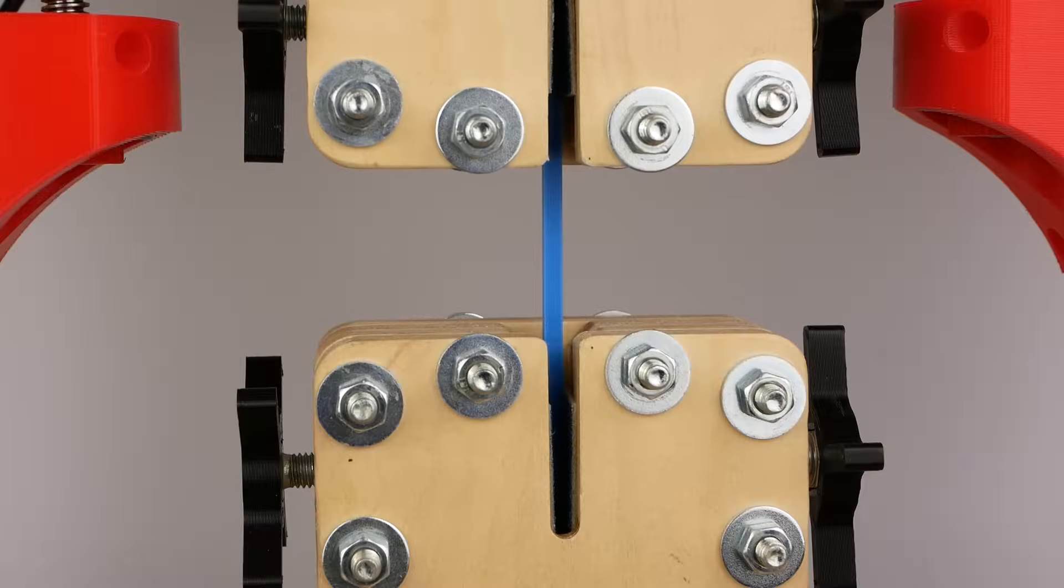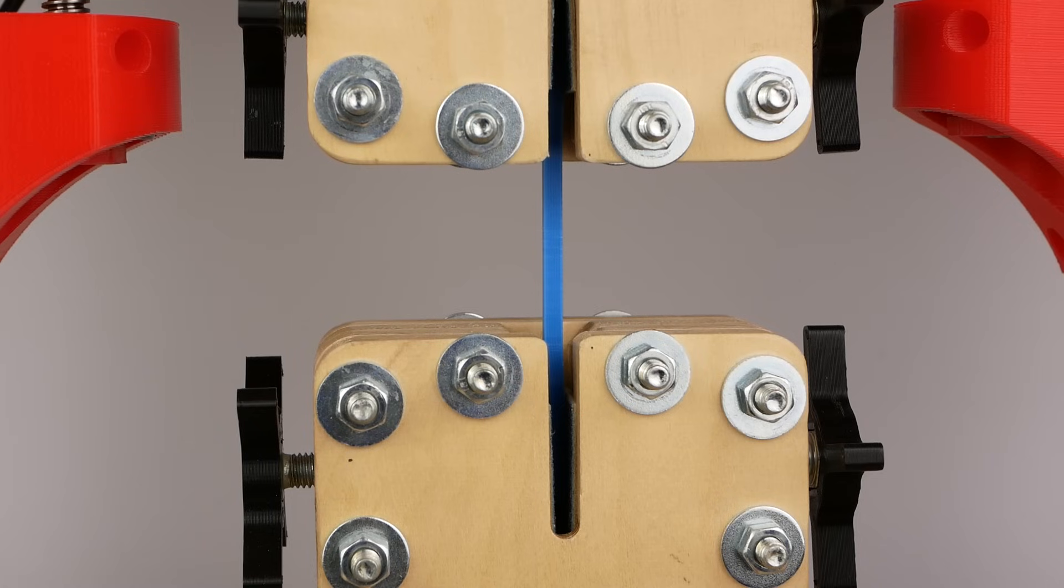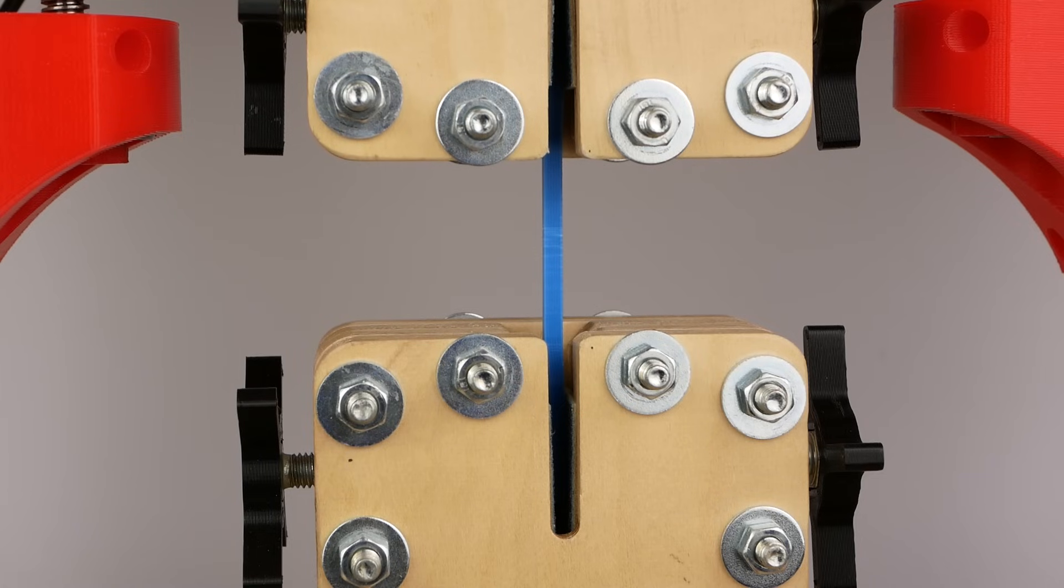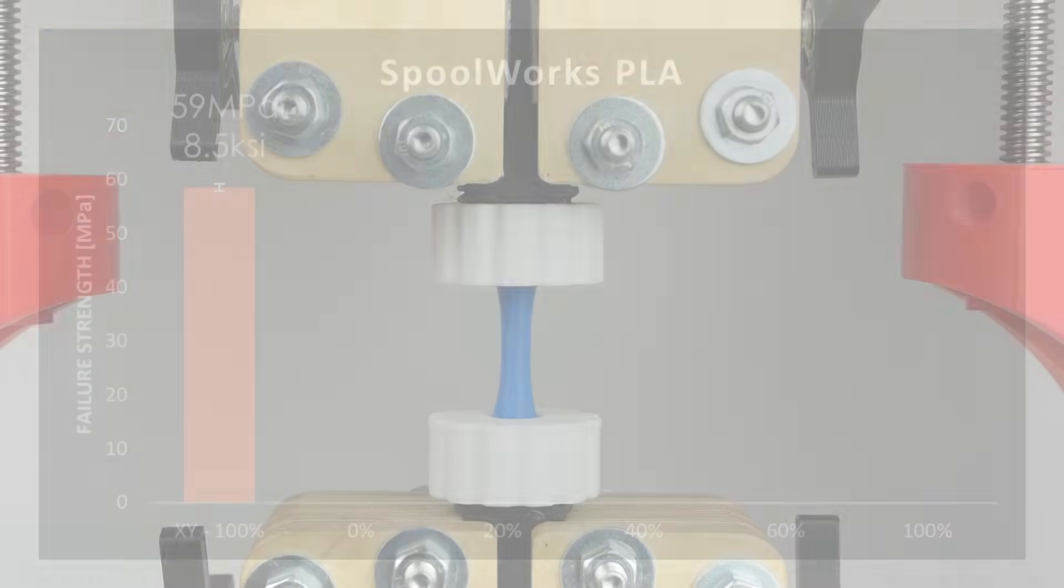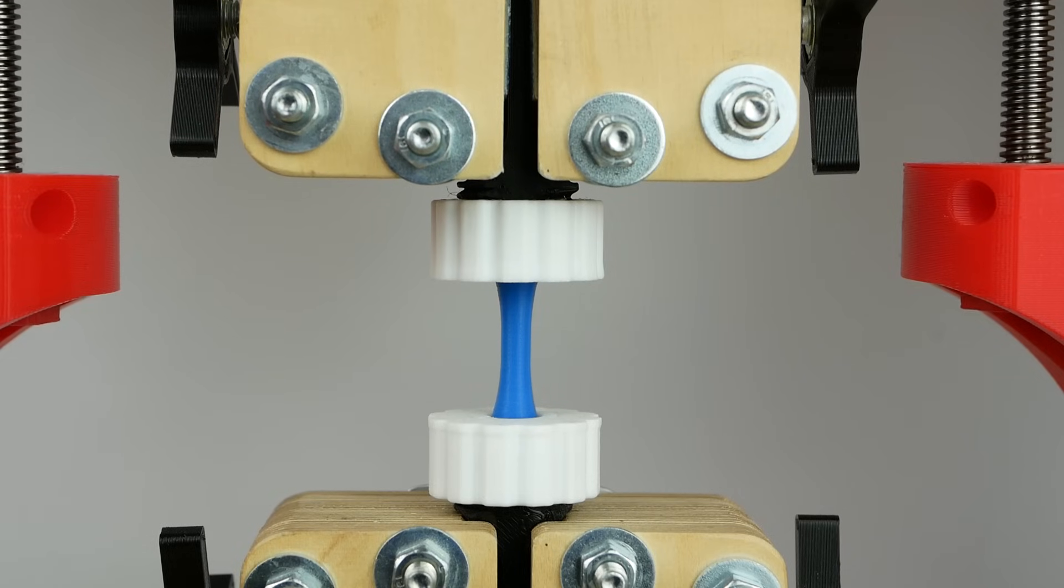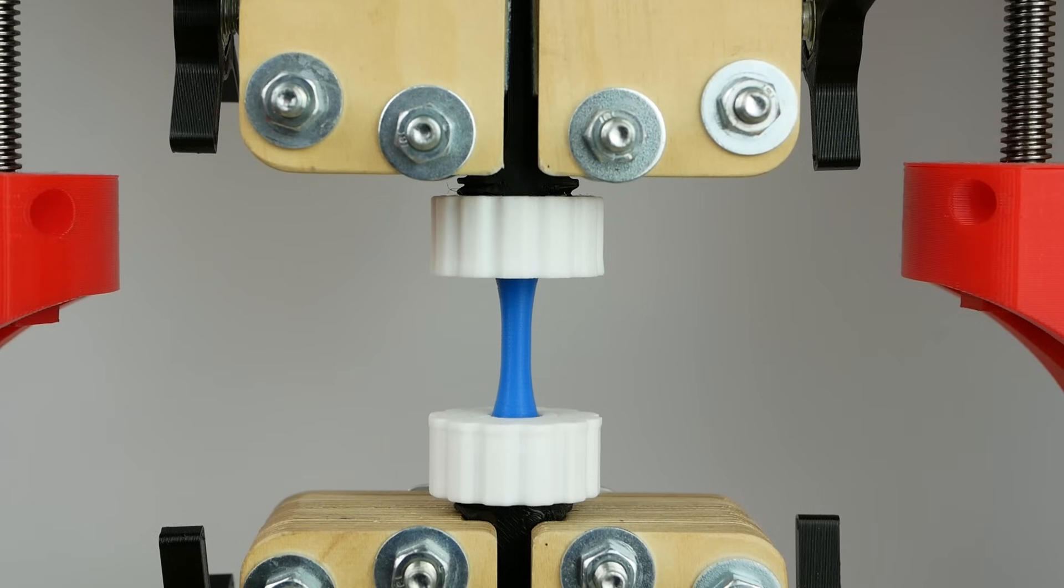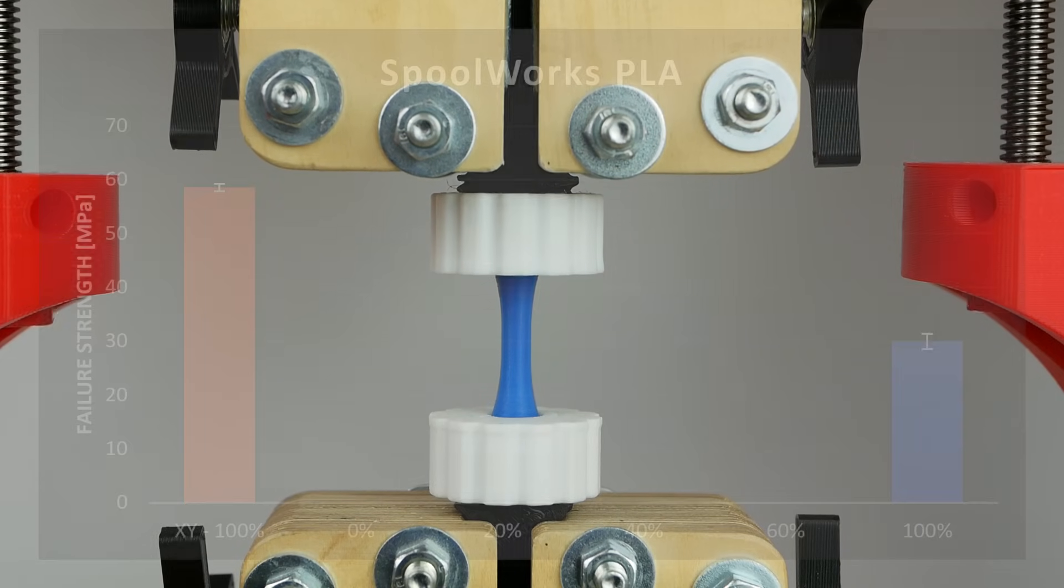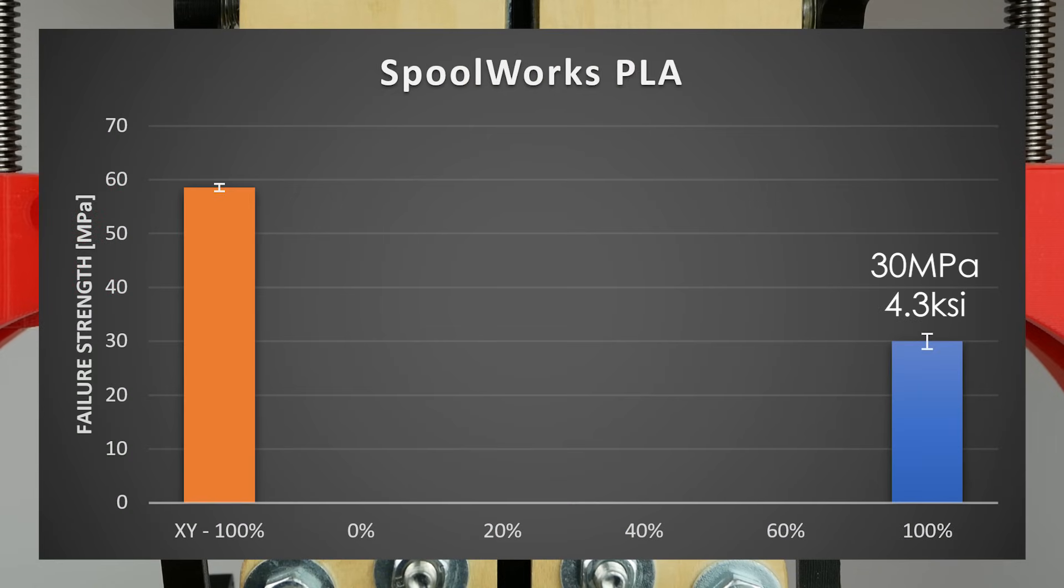The baseline that I printed lying, which should represent the ideal and maximum material strength, failed at 59MPa with only very little scatter. Next, we come to the layer adhesion samples where the ones with 100% fan speed failed at 30MPa so only half what the horizontal coupons were able to bear.